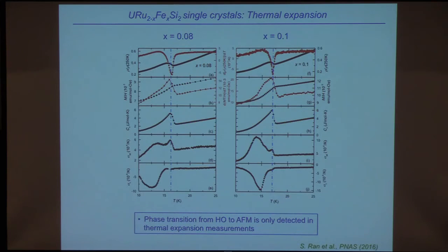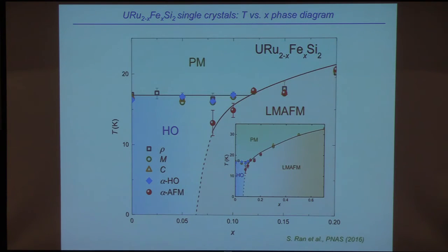And so that's shown here. Again, here are the features. I won't belabor you with the details. But from all of this, you can then construct a phase diagram of temperature versus iron concentration. So here's an overall view, and this is more detailed in the neighborhood of the transition point, right up here. Again, you see that this phase boundary is not vertical, and we're trying to measure in more detail what it looks like in this region right here.